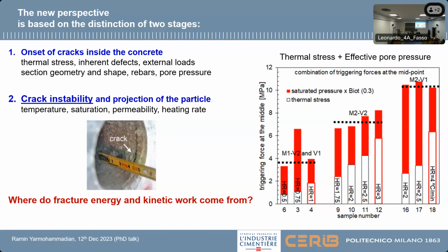However, my thesis is mostly concentrated on the second stage, which we think is more important, because usually when we assess structures after fire, we could see the crack which is there, but the instability of the crack was not completely done. If we have a crack which is there after the spalling, in our opinion, it's even beneficial, since the crack can act as a thermal barrier to reduce the temperature inside the concrete, and then it can prevent the rebars from being exposed directly to the fire. So predicting the second stage, which is the crack instability, is more essential.